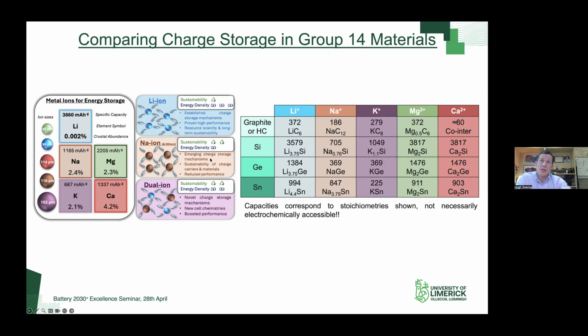Not quite as established charge storage mechanisms. So again, even within hard carbon, there's still ongoing debate in the literature around the exact charge storage mechanisms in hard carbon. But what you should be able to do, at least conceptually, is try and get sustainability of your charge carriers and also your materials. So the idea here is with an inbuilt energy density penalty because of the reduced capacity of the materials, you can increase the sustainability. So you'll see these two kind of emerging or diverging paths where the more sustainably focused battery chemistries are looking at sodium ion, for example, and then the high performance ones like in EVs are focused on lithium.